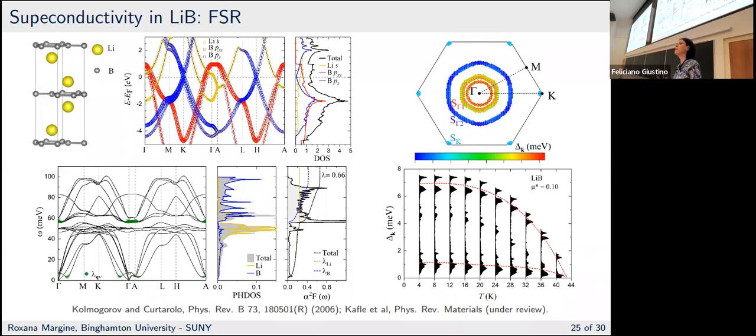This is still below MgB2, but what I want to point out here is that if you have a layered material and want accurate predictions, the McMillan formula is not going to be enough. For layered materials, you really need to go beyond this approximation and do an anisotropic calculation.